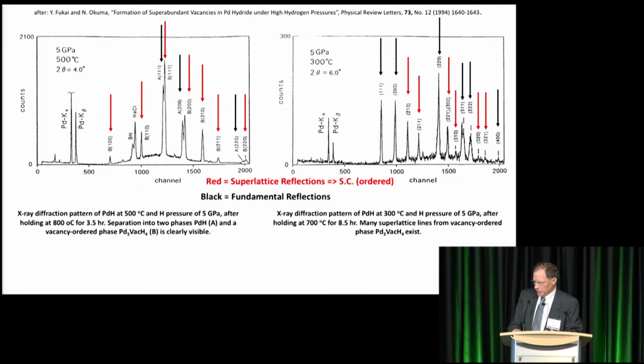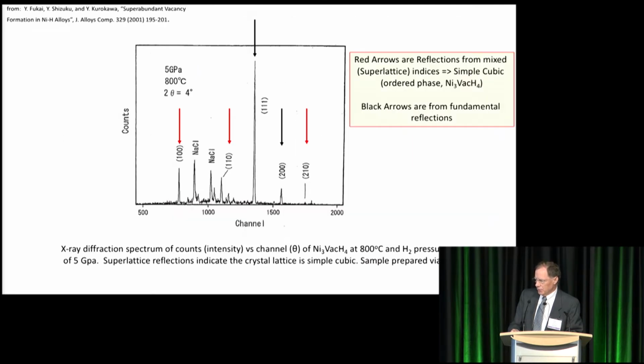I'm going to skip through this quickly. This is the X-ray diffraction proving that there is, in fact, that structure. This happens to be for nickel that takes on the same ordered phase, Ni3 vacancy hydrogen 4.